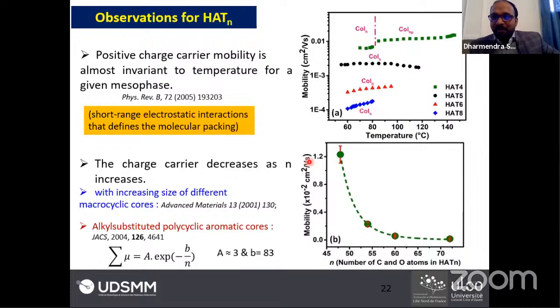So one important, interesting idea came to our mind: why is it reducing, and can we estimate any empirical relation for this triphenylene compound? We went into the literature and found that if we increase the core size, charge carrier mobility decreases. The first paper came with the macrocyclic cores in 2001. Later on, after 3 years in JACS, this empirical formula was again proved for alkyl-substituted polycyclic aromatic cores. But in our case, because the core is not changing and only the alkyl chain is changing, we justified the validity of this expression in our system.